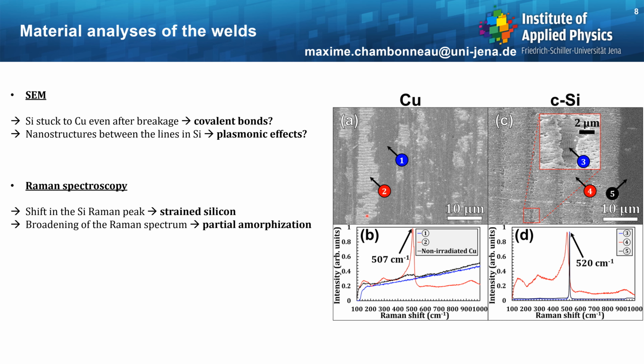We have also done some Raman spectroscopy measurements, first on the copper sample, and we have observed a peak looking like the one of silicon, except that it is shifted, which may indicate that these silicon parts here in white are strained silicon. And finally, on the silicon sample, the Raman spectroscopy measurements revealed a broadening here in red of the Raman spectrum, which may indicate a partial amorphization of the material.